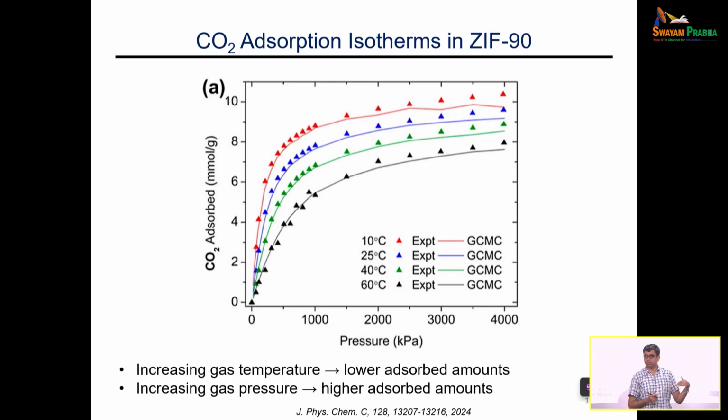Adsorption, like I said to start with, is expected to be an exothermic process. If you have higher temperatures, adsorption is going to be very severely impacted. So if you look at the first, this is 10 degrees, this is cold for a process. You can do it in the lab, but replicating 10 degrees in an environment, yes, you need cooling to get there, versus 60 degrees, which is probably the temperature for most flue gases, even after a certain length of the stack.